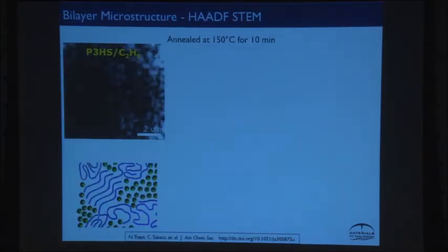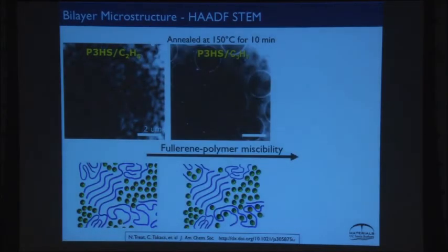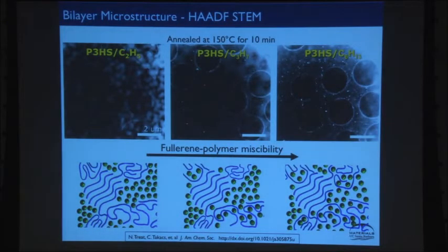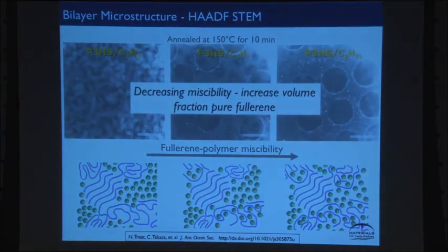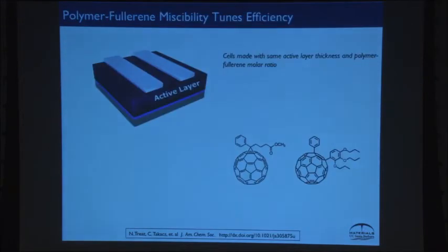So we went off and made a lot of solar cells. And sure enough, if we do TEM, and maybe it's a little blurry from my angle here, sorry about that, what we found was that the imaging of the domains tracked that solid state miscibility that we were measuring with SIMS. We found one that was not soluble at all, would precipitate out too well. This one would mix too well, and the one in the middle was somewhere in the middle. And so we thought, well, the one in the middle ought to work.